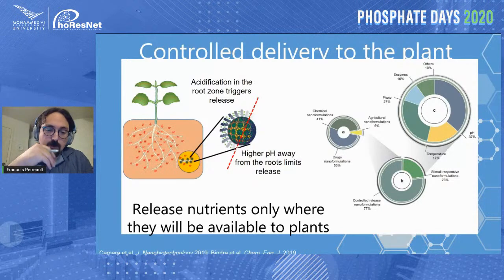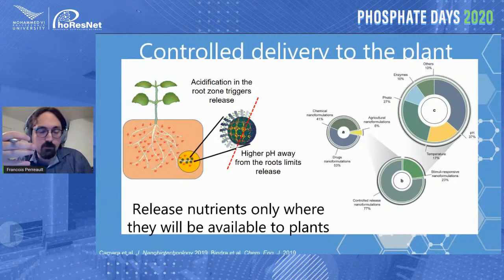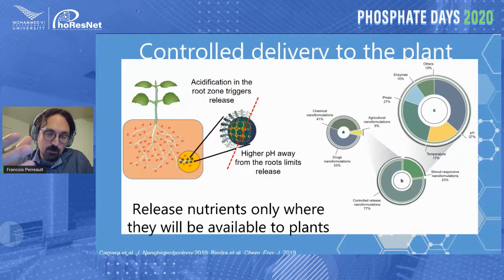This is a very interesting, very smart approach to controlled release, where they use a polymer that is pH sensitive. Since the roots with their exudates change the local pH environment at the root interface, when the particle gets in close vicinity of the root, the change in pH will trigger the release of fertilizer. But when the particle moves away from the root, the particle closes down and prevents the release of the fertilizer.